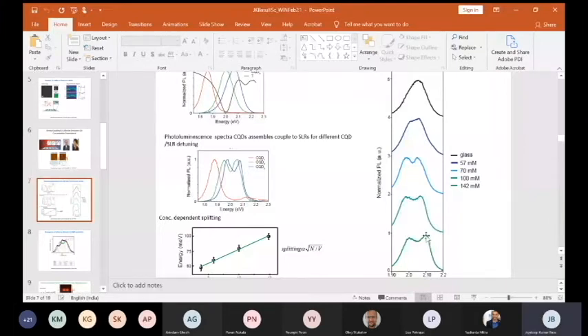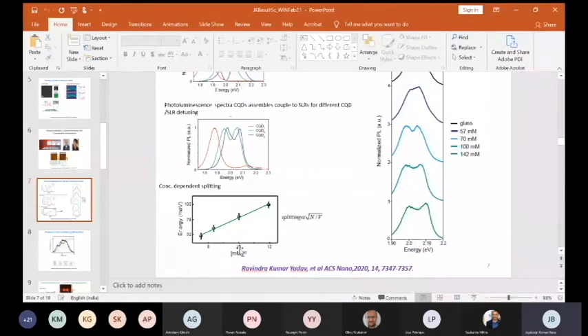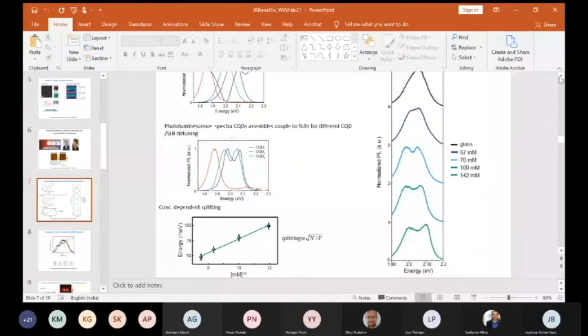When you plot it here, you see that it shows a nice scaling with the concentration, and you can see that approximately it scales with the square root of concentration. This is one of the telltale signatures of strong coupling. Essentially, one is seeing that the excitons in these quantum dots couple to these lattice modes, the modes present in the templates, and generate some sort of an exciton-plasmon polariton, which is what gives rise to this feature.